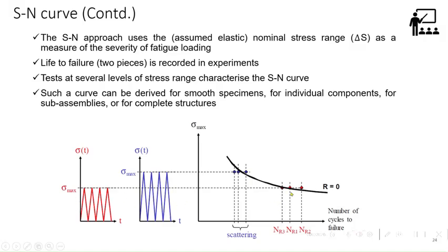It's showing 3 dots because your fatigue phenomenon depends on the surface condition, and unlike in static results, where you are not expected to have a variation of 1%, in fatigue easily 20 to 30% is allowed. So you will have a lot of scatter, then you join the points from beginning to end to get a SN curve.